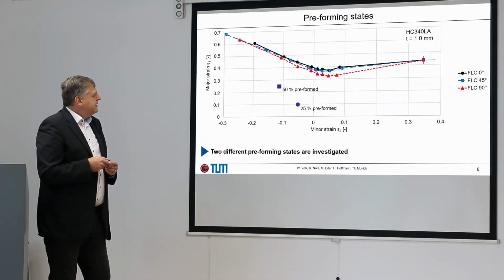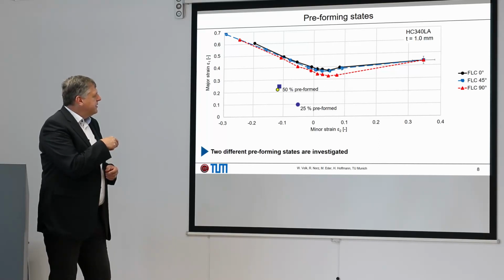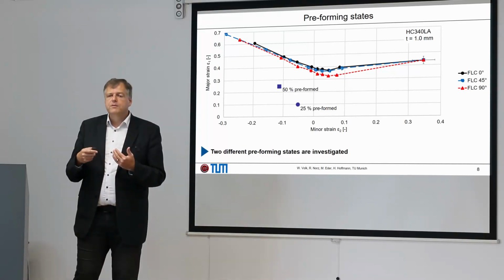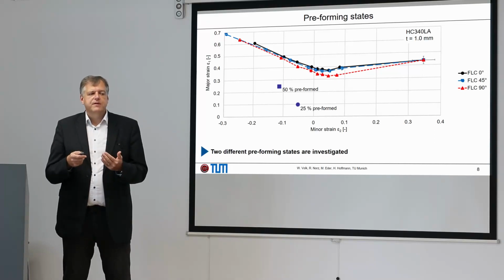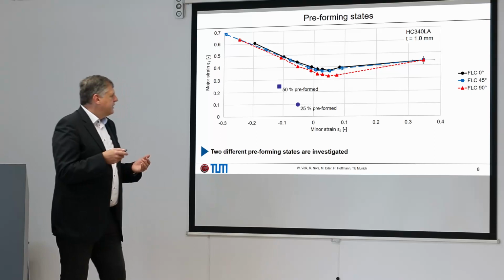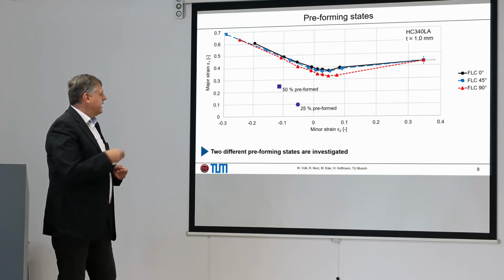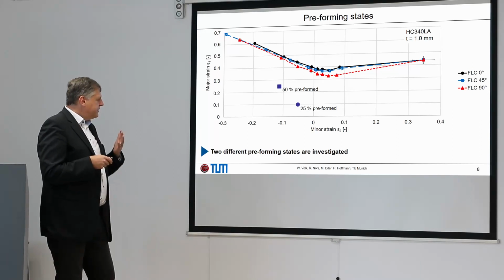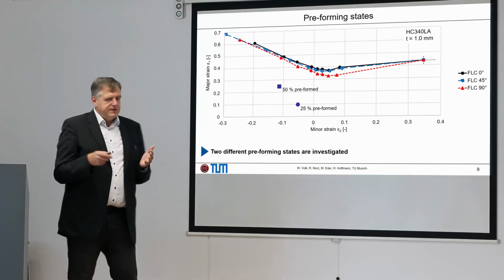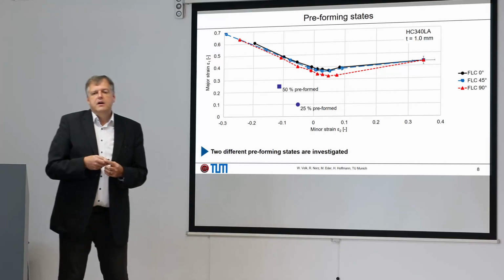For the analysis, we have seen here the 50% preformed, but also we wanted to prove how severe this effect is when we have a reduced amount of preforming. That means around 25% with respect to the FLC. So we have 2 different preforming states which are investigated in the following.